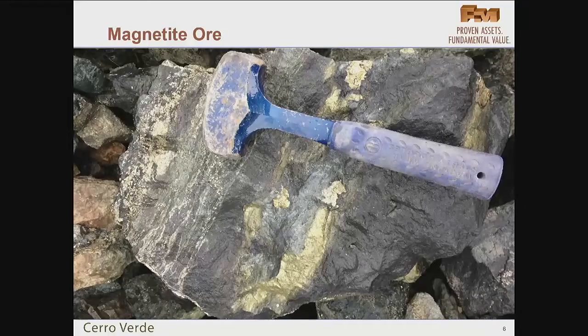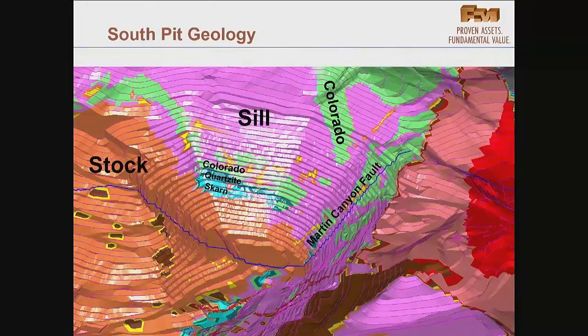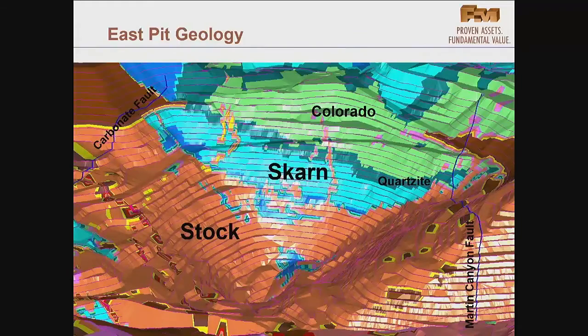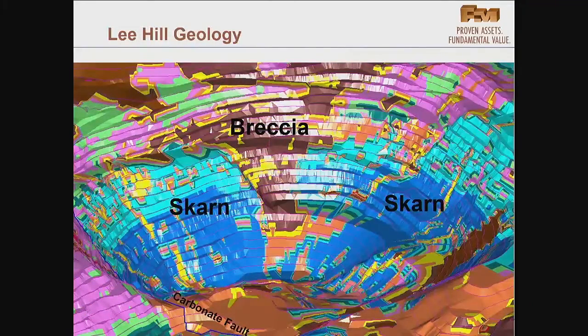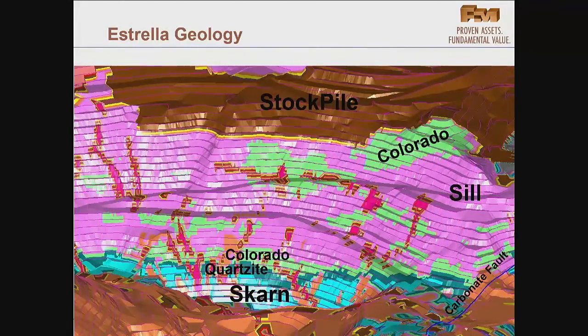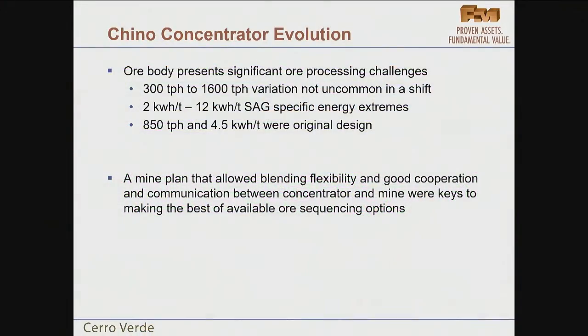Here's your magnetite, heavy stuff, a lot of pyrite. It complicates the operation of the SAG mill when you're combining it with 2.7 SG material. Again, kind of geologic conditions, looking in one direction you see some of the variation. To the east, similar variation, but different stuff. Lee Hill area where the heavy magnetite is, very, very complex. And finally, here's the other side of the pit. Again, extreme variation, no matter where you look. So very challenging. But that's all we knew.